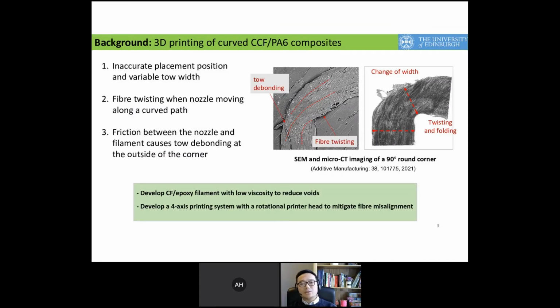These issues become more severe when printing curved passes. Fiber twisting and fiber folding usually happen at the corner, which could lead to inconsistent tow widths and inaccurate placement position. The friction between the nozzle and the filament would stretch the strip and cause tow debonding. This could block the later deposition on top and eventually terminate the printing process.